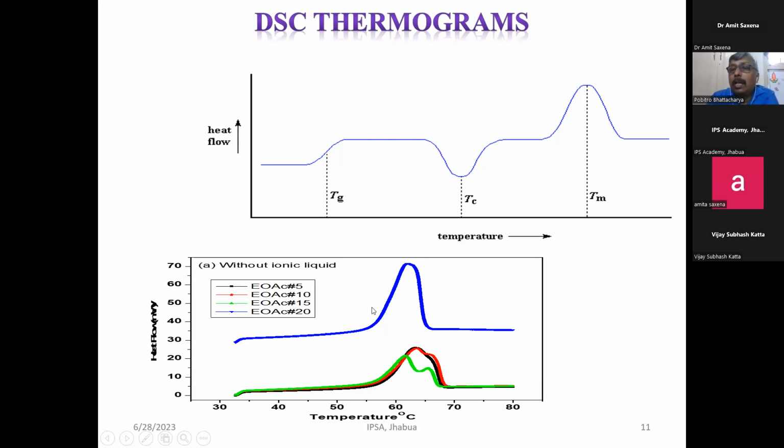The polyethylene oxide has a glass transition temperature around minus 60 degrees centigrade, well below room temperature, therefore it can nicely be used at any temperature below its melting. It starts melting somewhere closer to 60 degrees, varies depending upon different parameters, 60 to 68 degrees, sometimes even beyond. Anyway, minus 60 to plus 60 is a sufficiently wide range of temperature where it can be used.